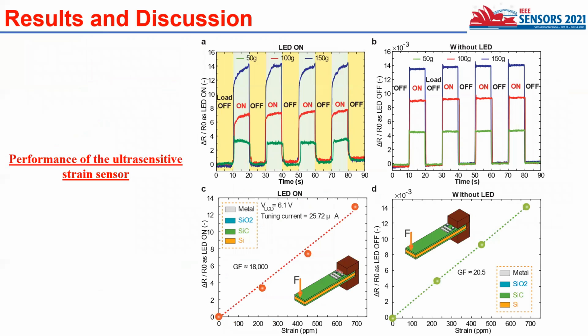After that, we investigate the performance of the sensor, and you can see here a comparison between the performance of the sensor under the LED and the dark condition. The performance of the sensor significantly improves when using the LED. For example, without the LED, the gauge factor of the strain sensor is 20. However, with the LED and the tuning current, the gauge factor is around 18,000.